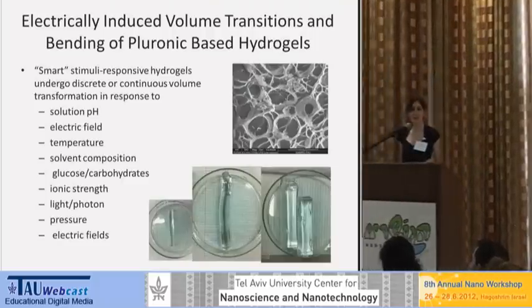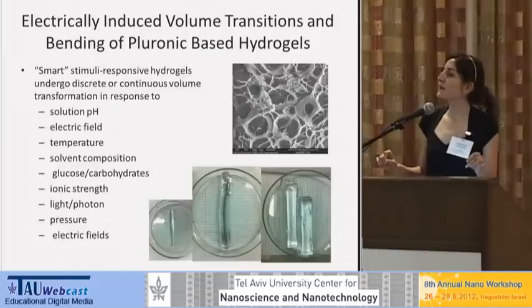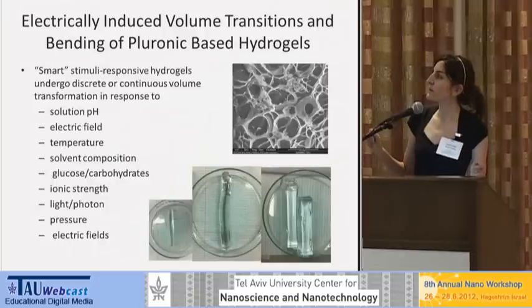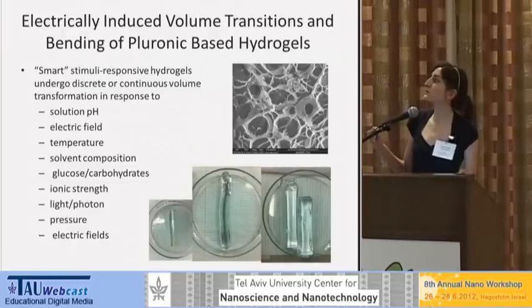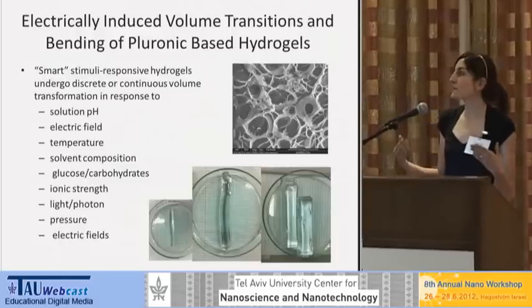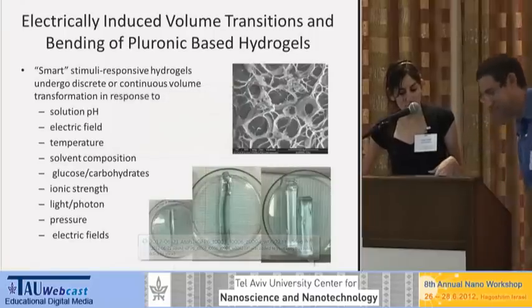Hi, I'm Leah Engel, and I'm a PhD student of Yossi Shacham and Slava Krylov. My main field is polymeric MEMS and electroactive polymers, but today I want to talk to you about a project that I've been spending a lot of time on recently, which is based on hydrogels, stimuli-responsive hydrogels, which undergo volumetric transitions as a response to the surrounding solution, for example, the pH, the composition of the solvent, the ionic strength. Interestingly, they also undergo volume transitions as a response to electrical fields.